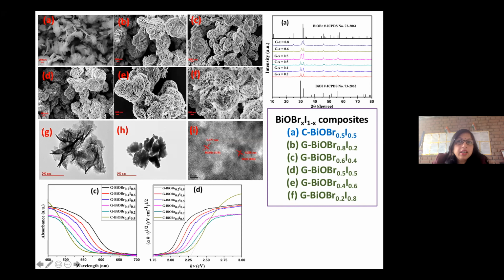So A is the chemical one, meaning the hydrolysis method without any leaf extract. Then B, C, D, E, and F are the images of the different ratios of BiOBr/BiOI. In all, you can see it is going to the nano one. Then to see which will be better, we did the studies. And G and H are the images of TEM. This is the chemical one, and this is the green one, and by HRTEM, we found these are the BiOBr and BiOI. Both lattice fringes were present in the composite, so it was confirmed that the composite has been formed.